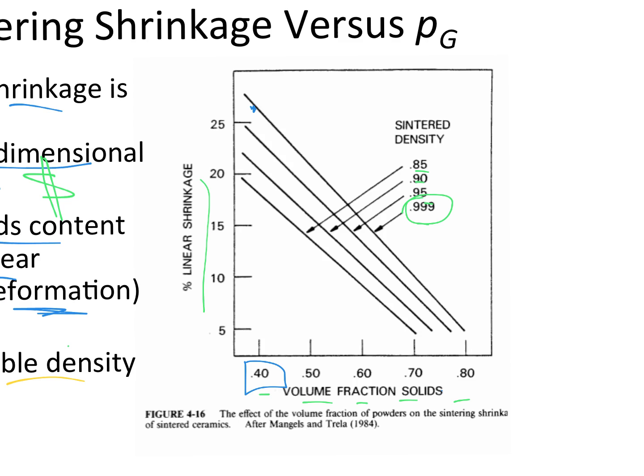The other side of the coin, of course, is that we can go to 80% solids loading, 70% solids loading. These are typical. So we're above body-centered cubic packing densities, but we still have a fluid that ideally makes a solid that sits at those densities. The nice thing about that is if we start at 70% and we're trying to get to 99, we have a 10% shrinkage. Or we start at 80% and we're trying to get to 99, then we have only 5% shrinkage. So it's a big payoff if we can do it. That looks good. It's a great story, and this course is the goal.